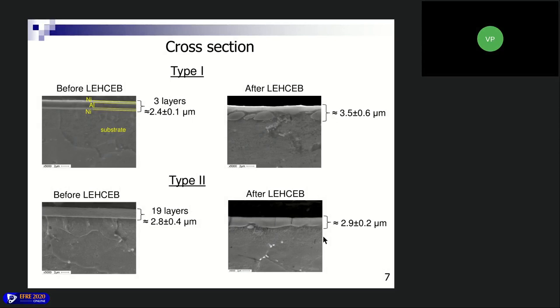If we look at the cross section of the samples, we can see the same structure as was shown on the previous slides. The three layers with a total thickness of about 2.5 micrometers, and for system number two, we have 19 layers. After the electron beam treatment, the 19 layer system shows quite a uniform thickness of the surface alloy. It's 2.9 micrometers or about, with a quite uniform border between the substrate and the surface alloy.